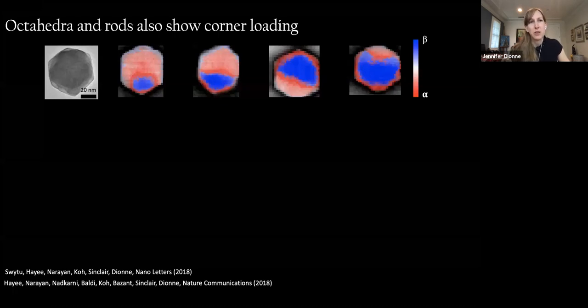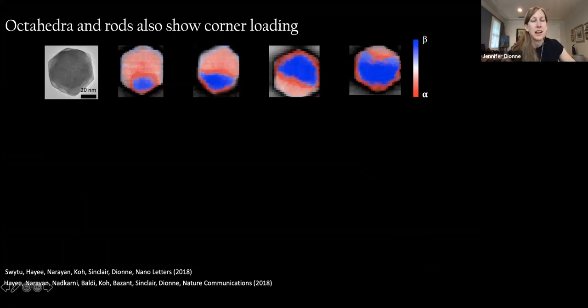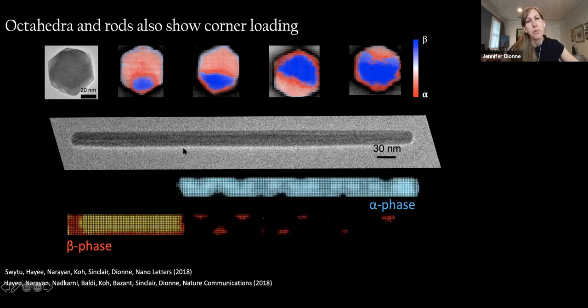Okay, so I wanted to share with you that it's not only the single crystalline nanoparticles that have corner loading. We can also look at octahedra. The reason we looked at octahedra is because those cubes were 100 terminated. Was it the surface termination, or was it the fact that the corners were 111 terminated? So we wanted to choose a single crystalline nanoparticle that had 111 surface terminations. Turns out that's less relevant than the low coordination number at the sharp corners. So it's really the corners that determine the corner loading. And you can get that also in polycrystalline nanoparticles, for example nanorods, where again the hydrogen intercalation is always going to begin from those sharp corners.